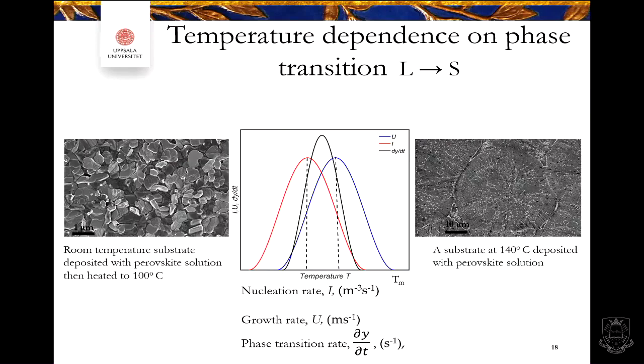So now we saw the different nucleation, and that is connected to the temperature also, how we heat those samples. When we use the spin coating technique, we have a substrate, we have our solution, we spin coat it, and then we put it on a hot plate. So we have a room temperature substrate that we put on a hot plate, so we have a slow crystallization. And when we do slot die coating, in our case at least, we heat our substrate before we put our solution on through the slot. And that is also to avoid humidity, because we are working in a fume hood and not in a glove box, and humidity is one factor that we have to be careful about when we work with perovskite.